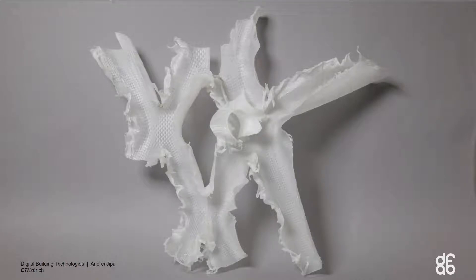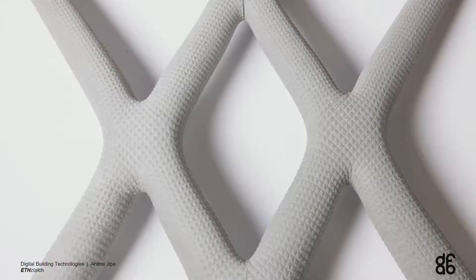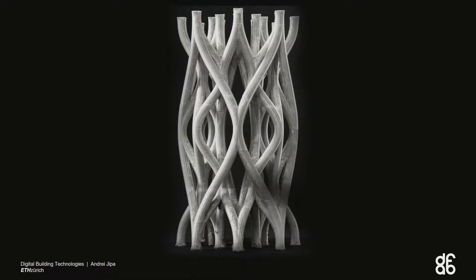The way we address this is to use a different 3D printing process which is based on plastic. The unique great thing about this is that we can actually make stable shells which are less than a millimeter in thickness. We reduce the specific weight of the formwork from 120 kilos to about 4 kilograms per square meter of concrete component. We still have a lot of accuracy in the details — about half a millimeter wide little prisms — and we inherit the geometric complexity very well.